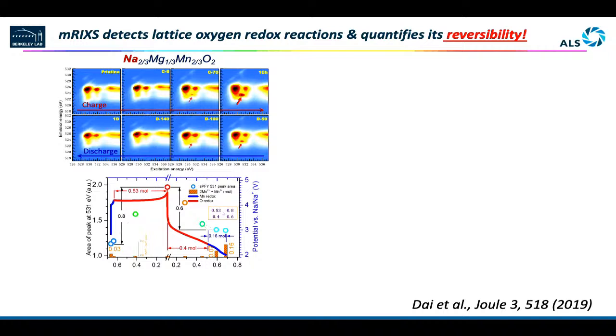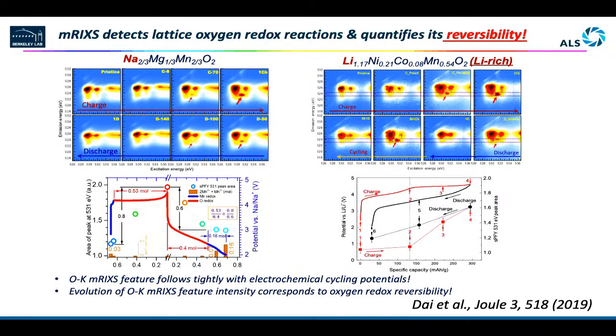So that indicates this kind of feature going up and down. It does indicate, to some extent, the reversibility of the oxygens going oxidized and reduced. On a so-called lithium-rich compound, as I said, I will come back to this material later, we see the same thing. However, the ratio never matches again.